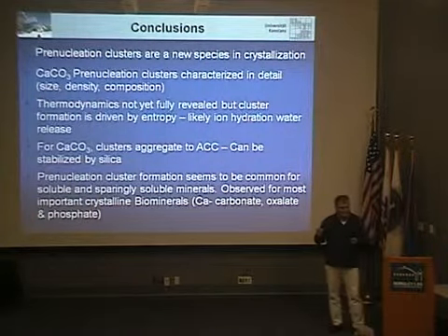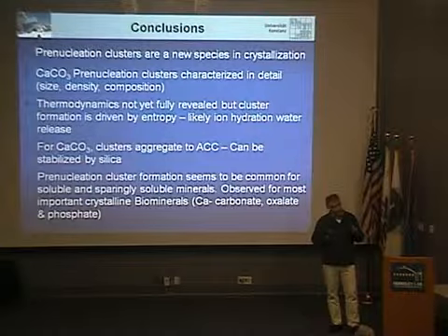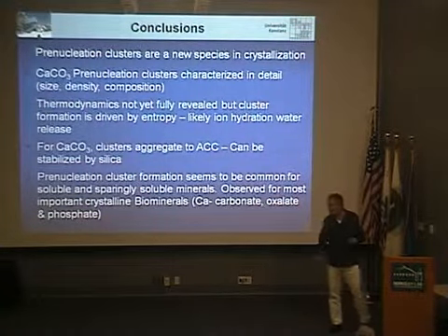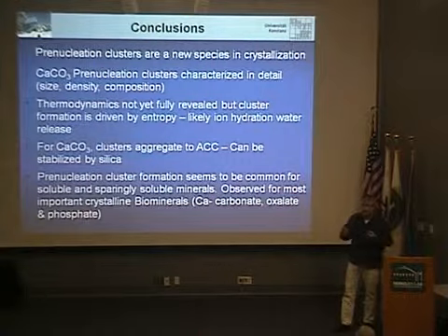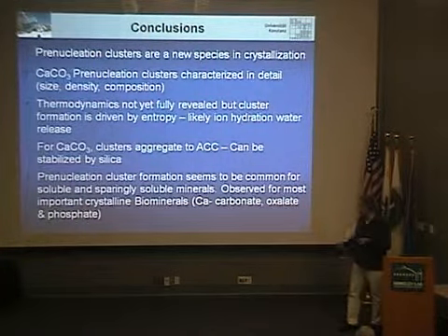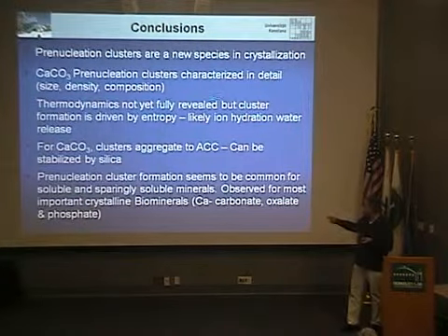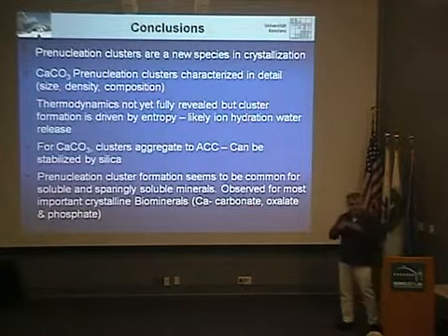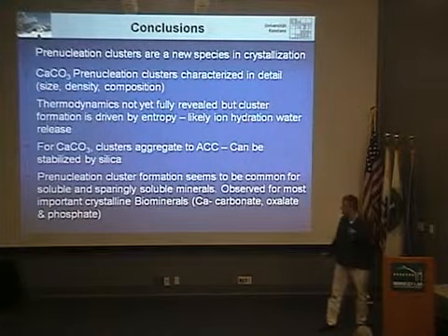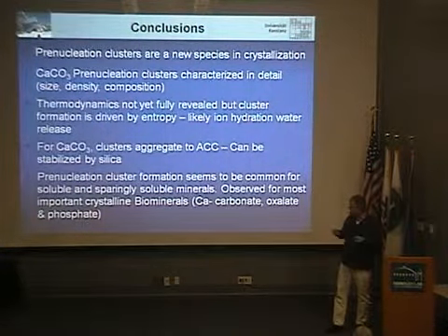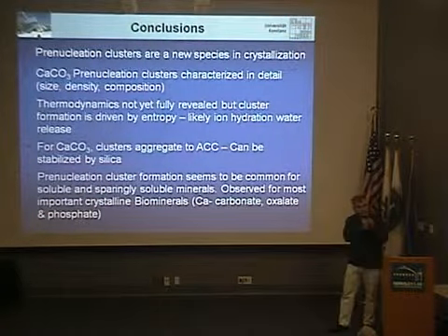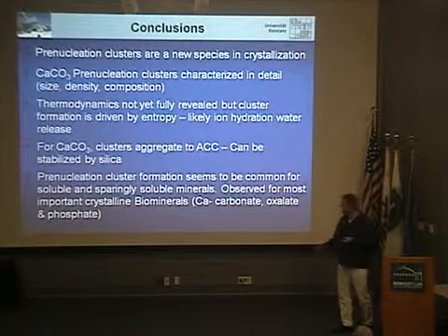I've shown you the ITC curve, the calorimetry. What we can say for sure is that the formation of ion pairs and clusters is endothermic as a sum. So that hints towards an entropic driving force, and this is likely driven by the release of hydration water. I've shown you some qualitative assessment via density calculations that about 18 water molecules are released when going from the ions to the clusters.